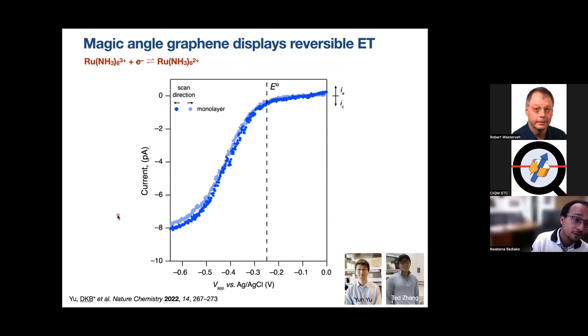Okay. And so then we can do a simple experiment called a cyclic voltammogram. In this experiment, all we're doing is sweeping the applied voltage between our electrolyte, which is in this pipette, and our twisted bilayer graphene surface. And we're measuring the current that is flowing across the interface. In this sense, we're sort of gating the material, but we're measuring the leakage current, right? For any of the physicists in the audience, the leakage current corresponds to the rate of interfacial charge transfer, where we're studying this very prototypical redox couple involving a ruthenium-3 to ruthenium-2